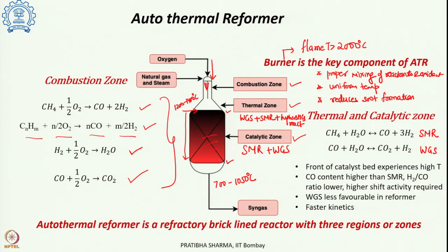At the same time, since there is a combustion reaction occurring in the combustion zone, the amount of carbon monoxide content in the autothermal reformer will be higher than in the steam methane reformer. Since CO content is higher, the H2 by CO ratio will be lower in the autothermal reformer. If CO content is higher, that means there is a requirement of high water gas shift activity. But we know that the water gas shift is an exothermic reaction and it is favored at a lower temperature. But the temperature inside the autothermal reformer is higher, as such the water gas shift reaction is less favorable in the ATR reformer.